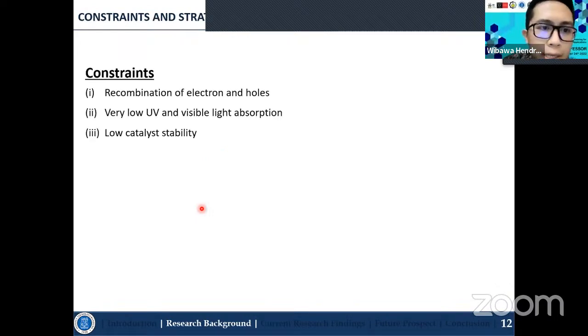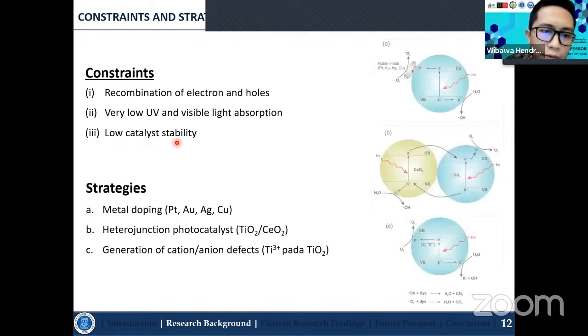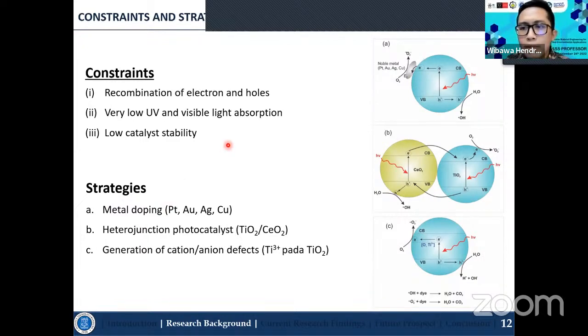Here are several constraints that have been overcome by research reported by our research group. The constraints are recombination of electrons and holes, as I mentioned before, very low UV and visible light absorption, and also low catalyst stability. Here we have three strategies: metal doping, heterojunctions for the catalyst, and generation of cation and anion defects. On the right-hand side are schematic illustrations of how these strategies work. The idea of these strategies is to increase the lifetime of the electrons in the conduction band, as well as to reduce the band gap so the catalyst can be activated by visible light, which has lower energy compared with UV light.